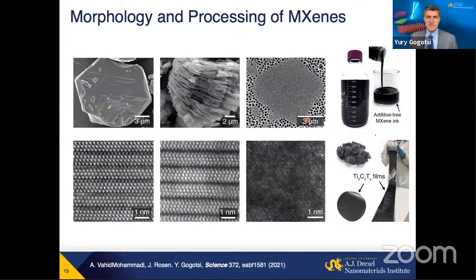One more important thing to mention here. You can find flakes which will be microns or even tens of microns made of graphene or boron nitride. Even for molybdenum disulfide, I have not seen solution-processed flakes larger than a micron because these materials are not strong enough.